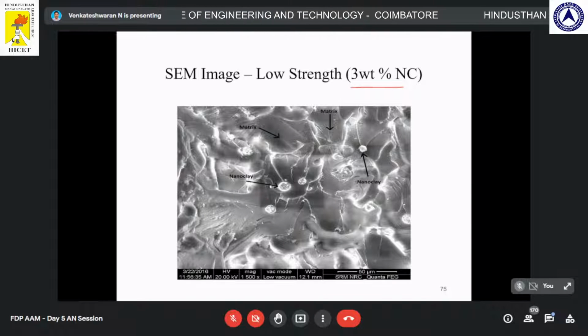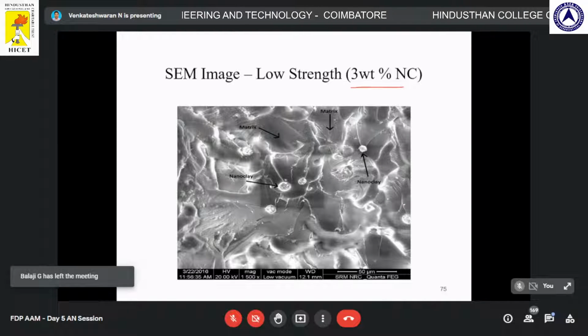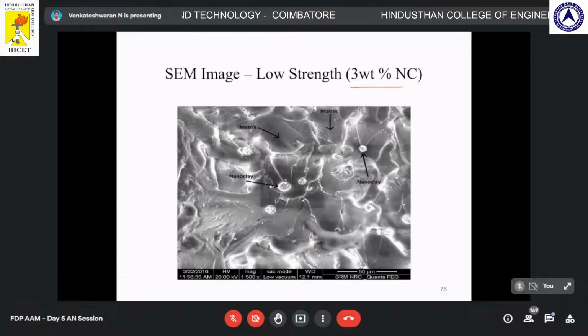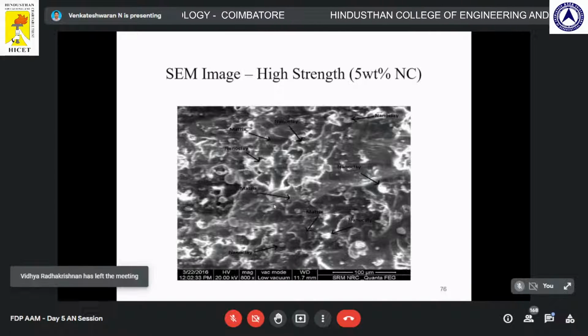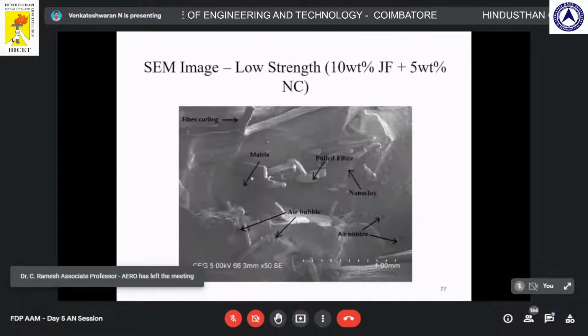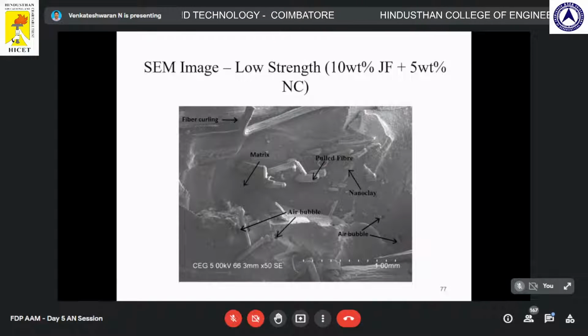We can see the nano clay distribution over a particular surface is very low. Whereas for the 5%, it was distributed throughout the surface, and hence it provides better mechanical strength or property. That is the reason why 5% nano clay is better. Then with the jute fiber and the nano clay, we can see the interface adhesion between the fiber and the matrix is very poor, and the fibers have not been properly adhered with the matrix.